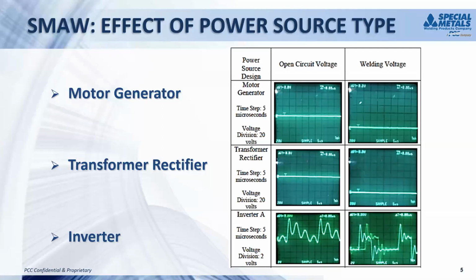And as people started getting some experience and some hard lessons learned, they have actually adjusted the inverters to be more friendly to nickel alloys because of the higher resistivity in the core wire. And to the point now, you can get a much smoother, more controllable arc with an inverter than you could in the past. But again, that difference in power source can cause a little bit of adjustment in parameters. The newer inverters do weld a little bit smoother, a lot better with the nickel alloys than in the past. And that will affect the performance of a stick electrode, and not negatively, but just something to be aware of, that there is a difference. Next slide.